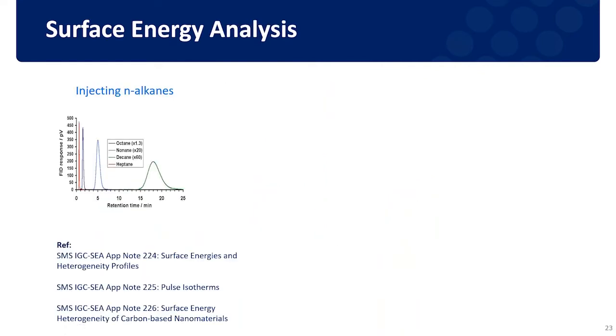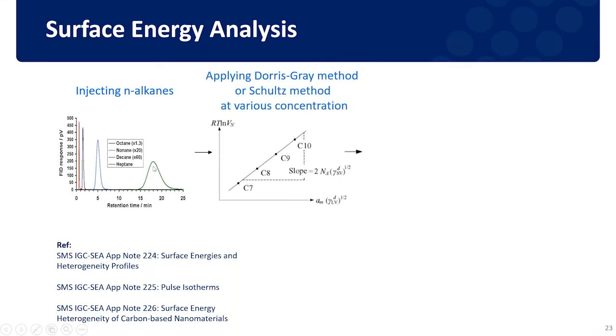So for the analysis of surface energy, normally we will inject a series of nonpolar solvents at the same coverage. And then from the retention time of each nonpolar solvent, we can apply the Dorris-Gray method and the Schultz method to get an alkane line here, which is normally a linear line. And from the slope and intercept of this linear line, we can then calculate the dispersive surface energy of the solid material. Then we can perform the same experiment at a series of different concentrations, at different surface coverages. Then we can get the surface energy profile with both the high energy sites on the surface as well as the low energy sites on the surface.